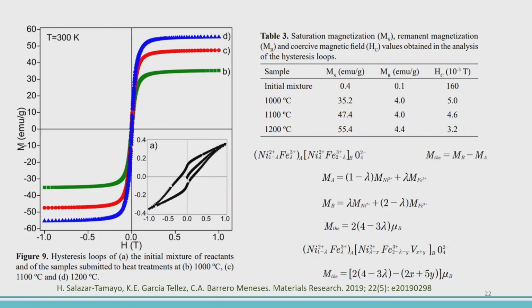We want to say that this is what we believe can be happening with the sample, and if we assume just cationic distribution, then this is the formula. We have here the saturation magnetization per formula unit per unit cell, and we have here the magnetization at the B site minus the magnetization at the A site. The magnetization at each site is due to the magnetic moments of the nickel plus that of the iron at the concentration, and this is for the B site. These formulas are known. Then using the electronic configuration, we know that nickel has 2 at the d level, and iron 5 at the d level. So we replace here, multiplied by Bohr magnetons, and then we find this formula here.